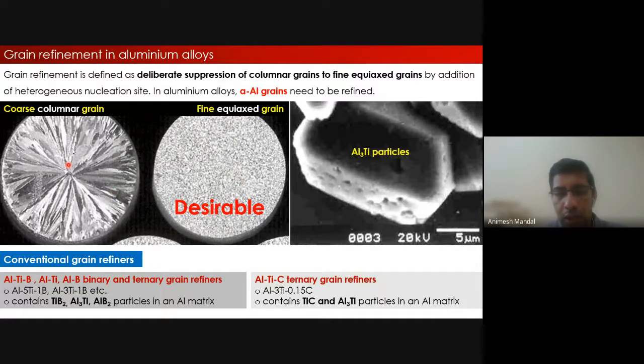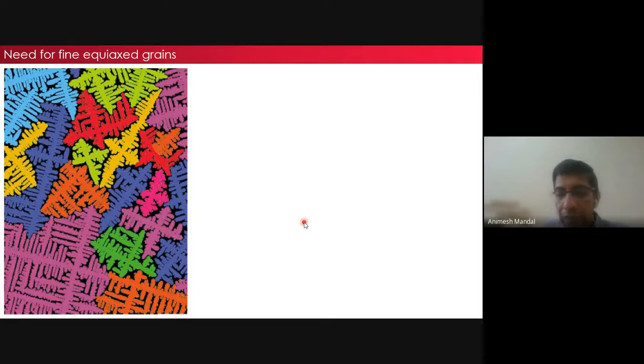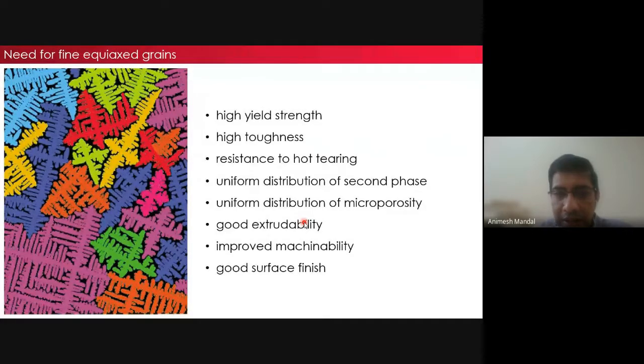You don't want this kind of microstructure. So why do we need fine grains? We spoke about strength, but it's not only the high yield strength that is improved by having fine grains. If you have fine grains, your toughness improves. There is also something called hot tearing, which means you will not see any cracks on the surface of the castings.